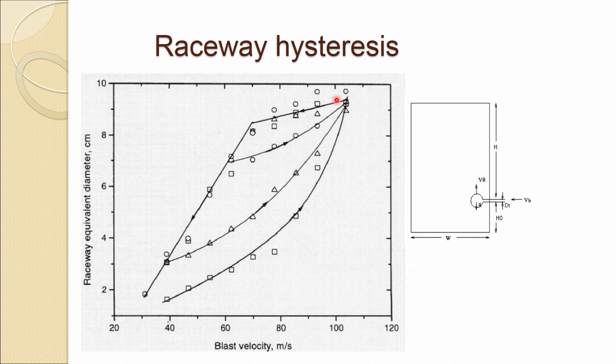almost 9.5, it is not reducing much. It is almost constant up to a certain velocity, and after that velocity it starts decreasing more linearly. And again, you stop somewhere and start again, it is going to follow the same path. When you start increasing, but when you start decreasing the velocity it follows the linear path, and when you are increasing it, it is following a non-linear path.